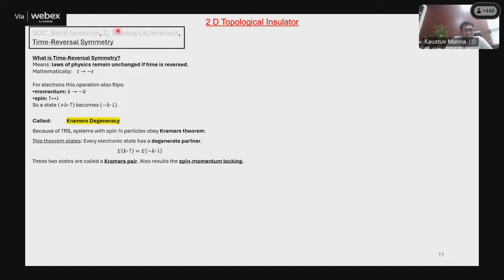Next, these are the three parts which I have already explained: SOC, band inversion, Z2 topological invariance. Now I am coming to time reversal symmetry. What time reversal symmetry does is that it operates on the time t, and under time reversal symmetry t goes to minus t. As a consequence, in momentum space, k goes to minus k. If you have a state with plus k and up spin, then after applying time reversal symmetry, the same state will become minus k and down spin. But you cannot have an intermixed state. That means you cannot have plus k with down spin or minus k with up spin. If you want minus k, then it will be down spin. If you want plus k, it is always up spin, because it is called time reversal symmetry.